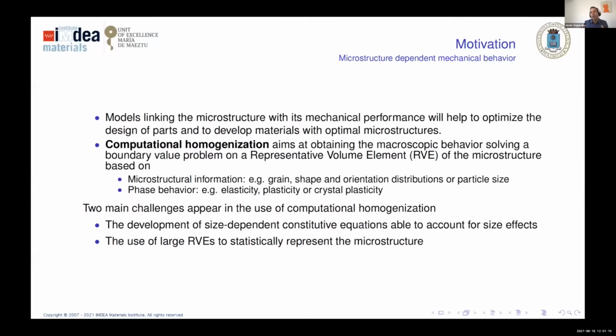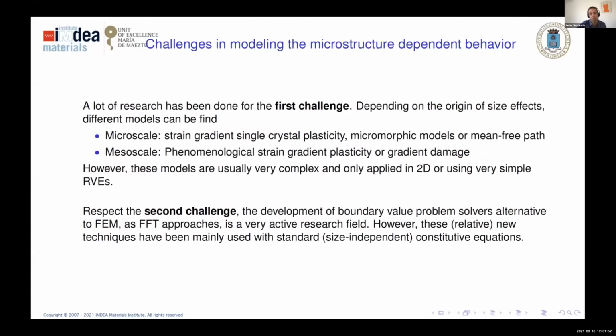And in order to reconcile these two aspects of size effects and computational homogenization, we have two main challenges. The first one is that we have to develop or include size-dependent constitutive equations or approaches if we want to capture size effects. And standard crystal plasticity, standard plasticity or some fracture approaches do not consider size-dependent behavior. And the second one is if we want to take into account the effect of the microstructure accurately, we need to use large RVEs, very complex, that represent accurately the microstructure.